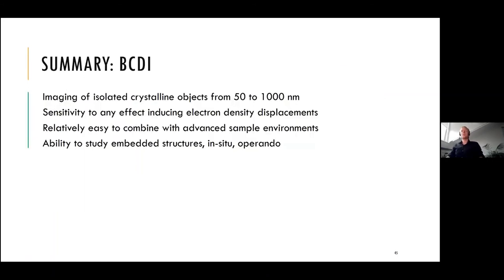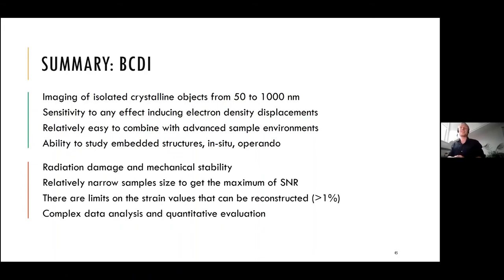So the overall summary about Bragg CDI is that we can image isolated crystalline objects from 50 to 1000 nanometers, that's a big range. It has sensitivity to any effects which induce electron density displacement or atomic displacements. It's relatively easy to combine with advanced sample environments. And most important, then we can go to study heterostructures or do experiments in situ and operando. And the negative sides: we get radiation damage and mechanical stability issues. It requires a relatively narrow sample size to get the maximum signal-to-noise ratio and the best results. And there are limits on the strain we can actually reconstruct, normally not more than 1% strain. And sometimes the data analysis can be quite complex.